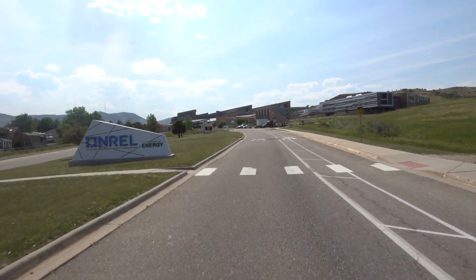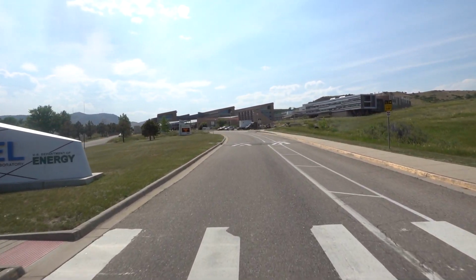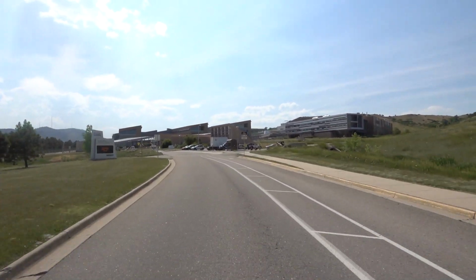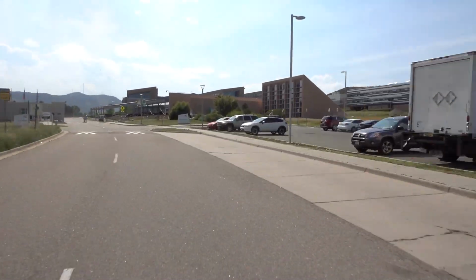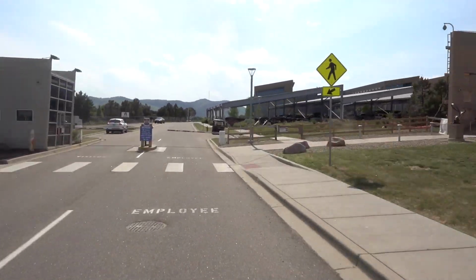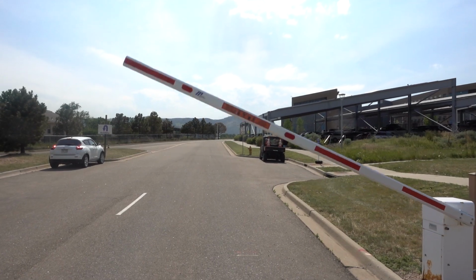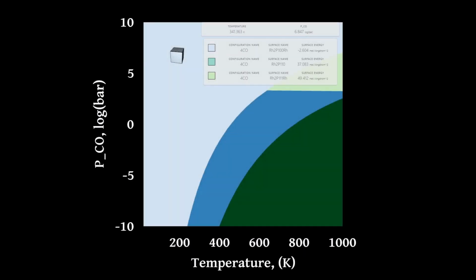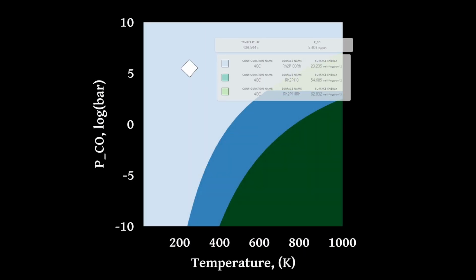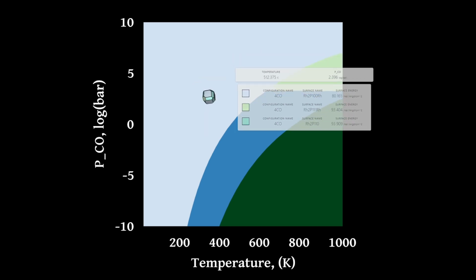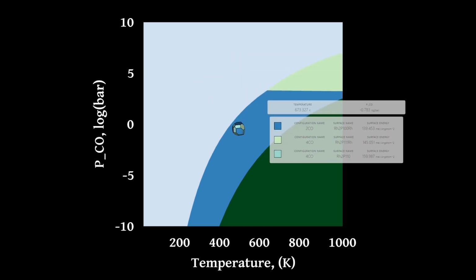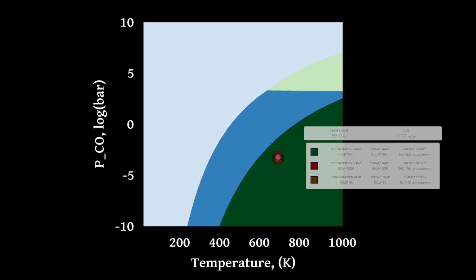Metal carbides are promising catalysts for many biomass-related conversion processes, but at the same time, the degree of tunability that enables this promise also makes it difficult to identify specific catalyst structures that promote targeted chemical transformations. One way that we handle this complexity is to engage our computational modeling team early in the process to help identify key phases, compositions, and surface structures to increase catalyst selectivity.